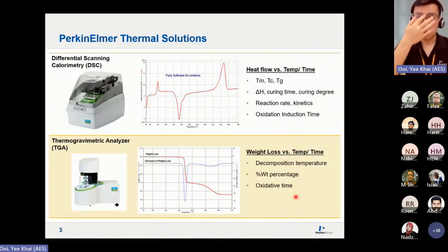So now you have DSC. It looks like this. What is the information that we can get from DSC? Usually it is Tg. Tg usually occurs at lower temperature. Sometimes for semi-crystalline materials, these are the terms that later we can go further into. You might encounter a crystallization peak, or what we call a cold crystallization peak. Now this is during heating. This is actually the reorganization of the molecular chain within your materials. And then, of course, this is melting.